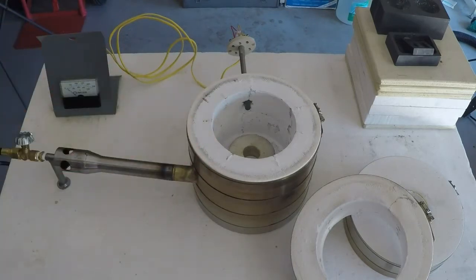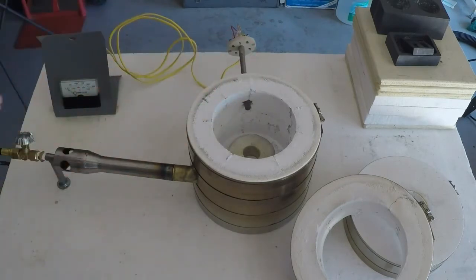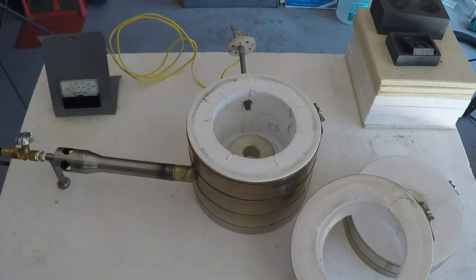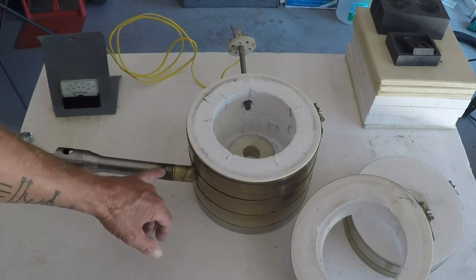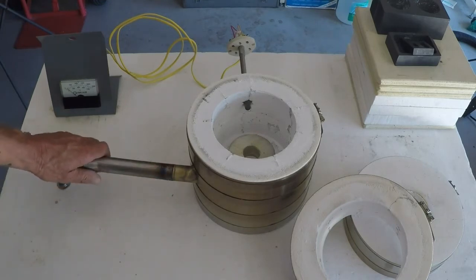When I first light the burner, it's going to kind of pop and snap and make a chortling noise. Then once the combustion is taking place in the kiln, it's going to just sound like a jet—that's what you want. You also don't want the tip of your burner exposed to the circular flames in there because it'll overheat the burner. When the burner is operating properly, it will get hot about to here, which is discolored, but back here you can actually touch it—it remains at room temperature because of the propane and the atmosphere going through it.